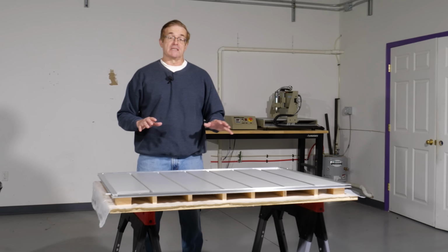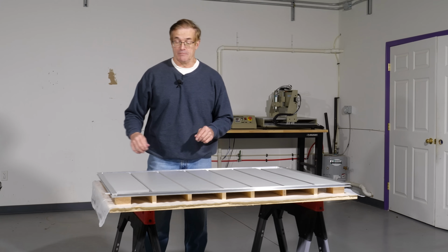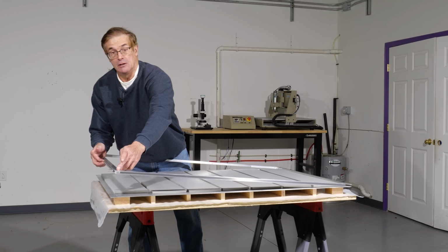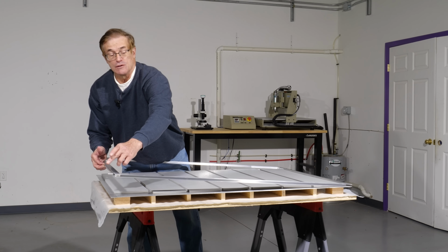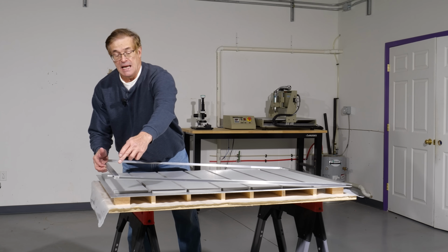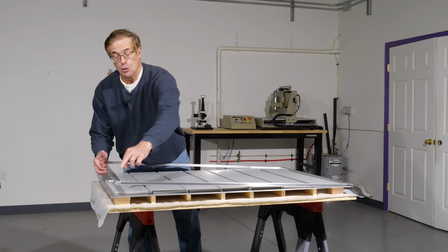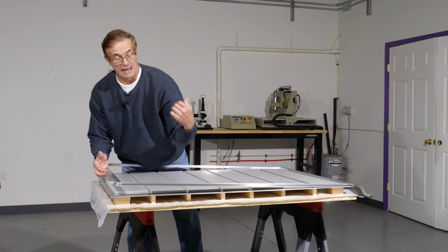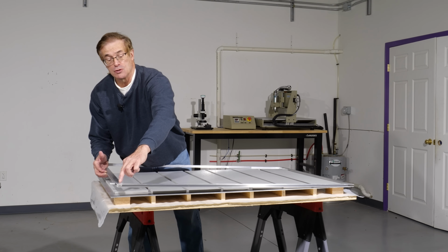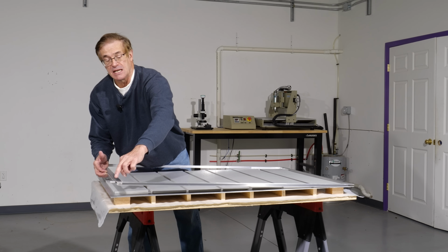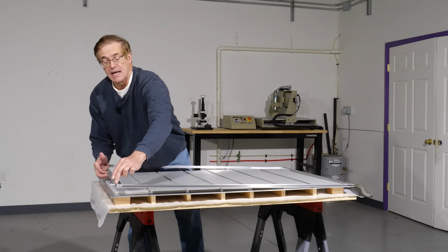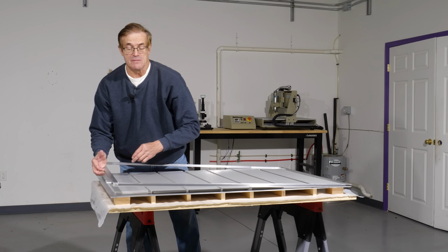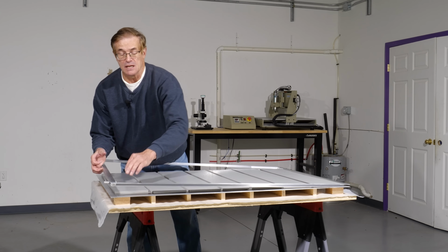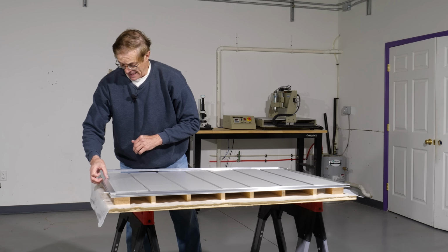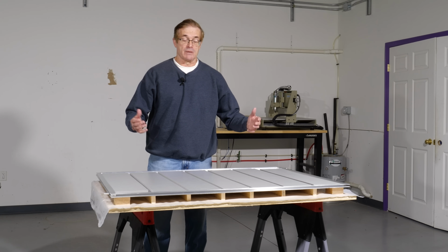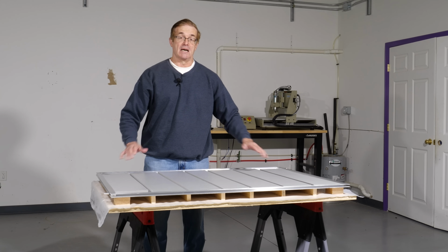So using that same sort of design, we built this. And let me show you how it's put together. I took some aluminum U-channel and miter cut the corners and welded them to form this rectangular structure here. And then bored a couple of holes in opposite corners, placed an aluminum fill tube and exit tube. And then once it was inserted into the hole, I then took some toughened epoxy and floated around the outside of the tube to make it nice and rigid and provide a leak-free seal. This frame then is located on a piece of 1 millimeter thick sheet aluminum that acts to seal up the bottom surface, and there's a mating 1 millimeter thick piece of aluminum sheet that fits on top.